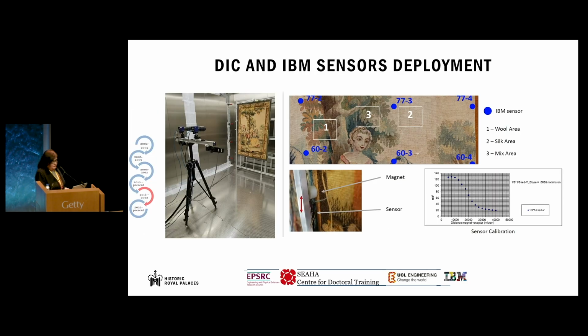Following on from this work, as part of Pedro's research project, we purchased a small 19th century tapestry to perform hygroscopic tests in an environmental chamber. The response of the tapestry was measured using IBM sensors, which are highlighted in blue in the image, and also a 2-camera stereoscopic DIC system was set up and calibrated to record the area you can see again on the slide.